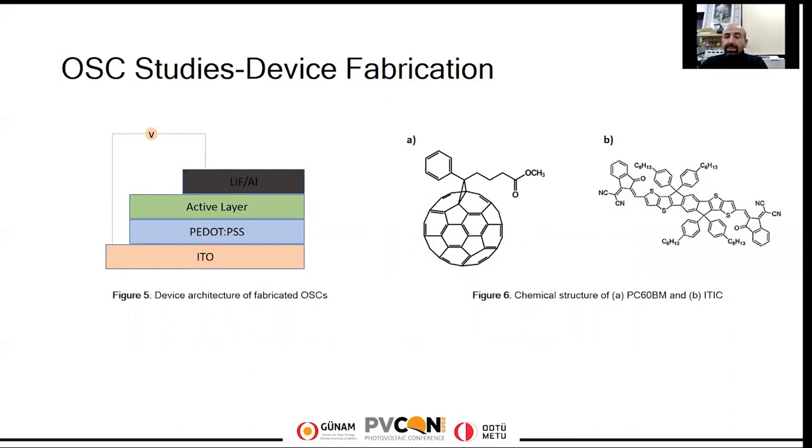Fullerene derivatives, with astonishing features and the super ability to create fast separation in the blend, led them to be utilized in bulk heterojunction devices as promising acceptors. But there are various drawbacks, like high cost of production and purification, vulnerability to air, limited light absorption, and some difficulties faced in adjusting the optoelectronic properties. These aspects brought a challenge in increasing the efficiencies of organic solar cells. That is exactly why non-fullerene acceptors have caught great attention.